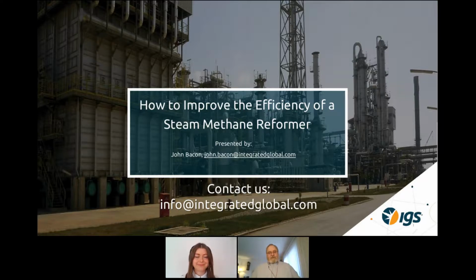Steam cracking furnaces, we've not done a lot in ethylene furnaces. We started off in ethylene and had a few inconsistent results, and mainly not because of the performance of the coating. The coating works very, very well. But in ethylene furnaces, there's a lot of duty, similar to steam methane, but even more so, a lot of duty in the convection sections. And we found that the benefit we were giving in the radiant section, we were losing in the convection section.